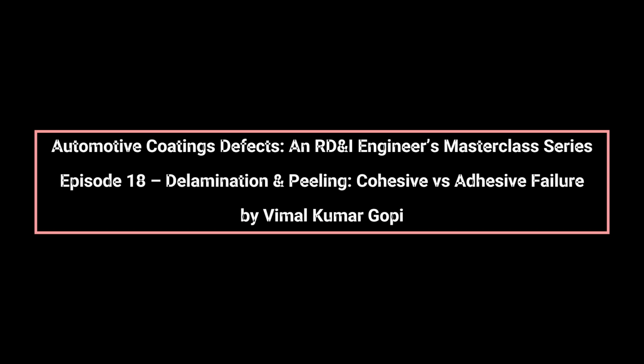Bake profile and cure kinetics are often underestimated contributors. Rapid oven ramps can lock in stress before the coating has time to relax. Overbaking increases cross-link density, reducing flexibility and impact resistance. Underbaking leaves residual solvents and incomplete cure, compromising long-term strength. OEM RD&I teams validate bake windows not just for hardness and solvent resistance, but for stress relaxation and durability under cyclic loading.